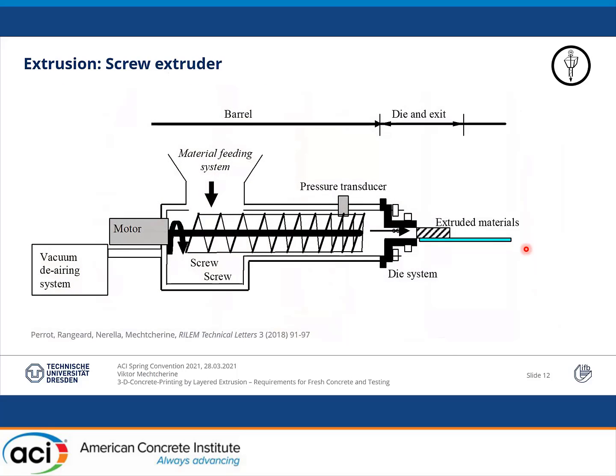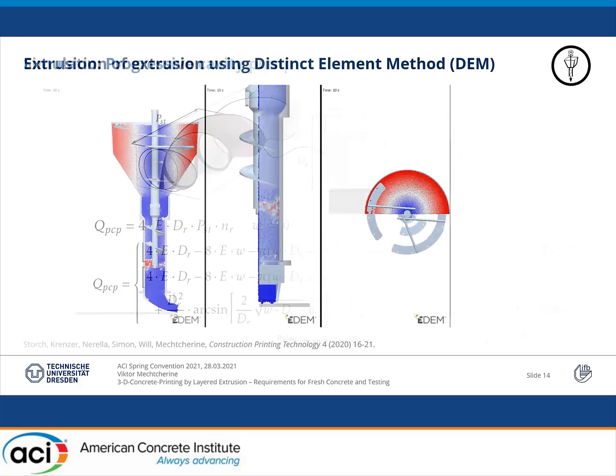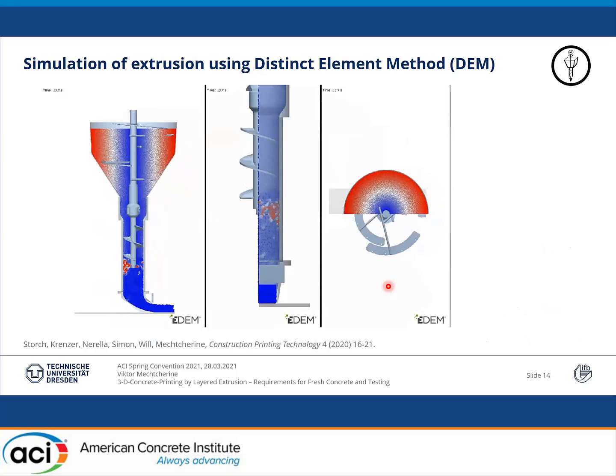In the scale of a printed element, even minor extrusion errors may pile up to considerable damage. Screw extrusion is the most common extrusion technique. Here, fresh concrete or mortar is subject to a very complex flow field with different shear histories and pressures. Unfortunately, we do not yet have formulas for estimating force–flow rate relationships based on rheological properties of fresh concrete. Indeed, even estimating the flow rate is challenging for such complex fluids. This works best for progressive cavity pumps, which have been used in the context of concrete 3D printing in order to stabilize extrusion flow. To predict the forces needed to convey fresh concrete in such extruders and derive adequate analytical formulas, we will need numerical analysis.